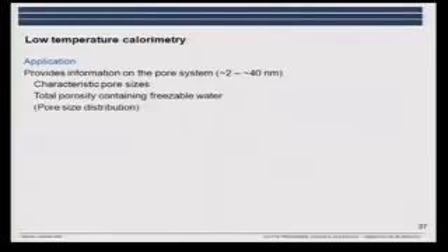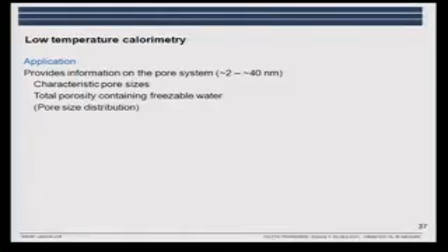Low temperature calorimetry is not that much used, but as it can be used on virgin samples, not dried samples, it has a potential which we want to look more into, and it will be used in connection with the product we're looking at. It provides information on characteristic pore sizes, and if the pore sizes are large, it is difficult to determine the pore size. Typically it would be in the 2 to 40 nanometer range. We have information on the total porosity containing freezable water, and from the heating curve we can obtain the pore size distribution, again for the part of the porosity where we have freezable water.